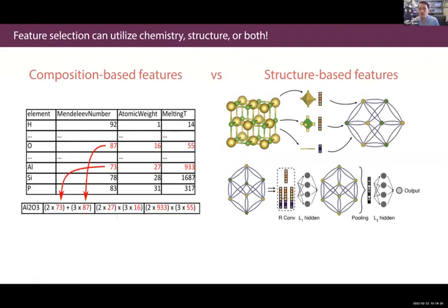If you know anything about materials informatics, you know that some of the hottest research happening in this area is in representation. Like, how do you represent materials so that a model can learn from them? And there are sort of two main ways to do it. You can use the composition, meaning you give it the chemical formula, and from that chemical formula, we extract some big vector that encodes all the chemistry you could for those individual elements in some combination based off of the chemical formula. That's what we call a composition-based feature vector, and our group has done a lot of the pioneering work there. But there's another approach, which is to rely on structure. If you know the crystal structure ahead of time, well, heck, you can look at bonding and orientations and all that jazz, and you could turn those into a feature vector, right?